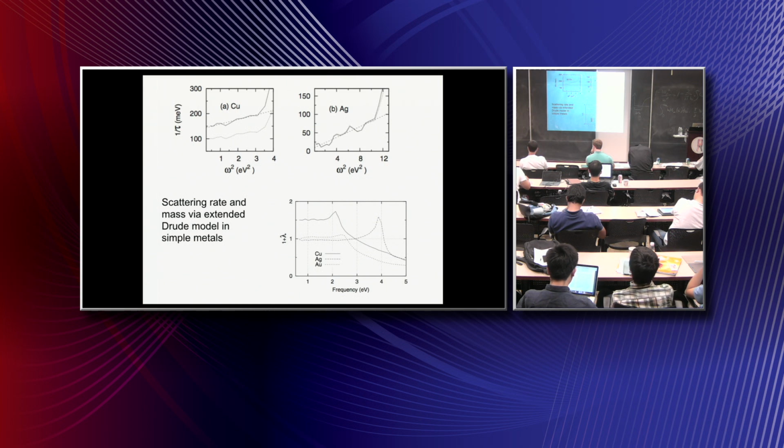But imagine I excite an electron-hole pair with 21 millielectron volts. Now that electron-hole pair has a new route to decay: it can create an optical phonon of 20 millielectron volts and still have 1 millielectron volt left over for itself. Okay? So the point is that this scattering rate can be strongly frequency dependent, and this is what is done, if you will, as a first step for understanding interaction effects in systems.